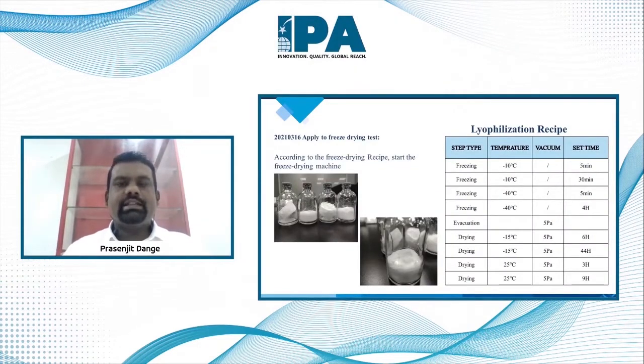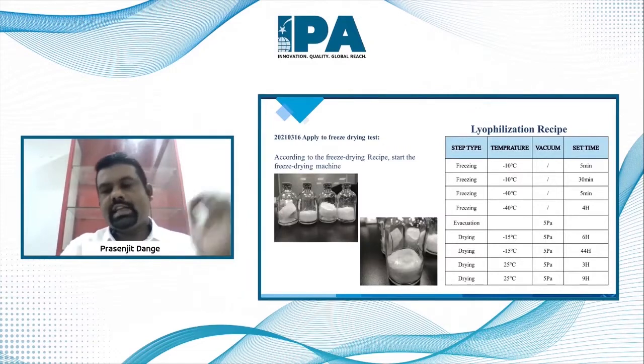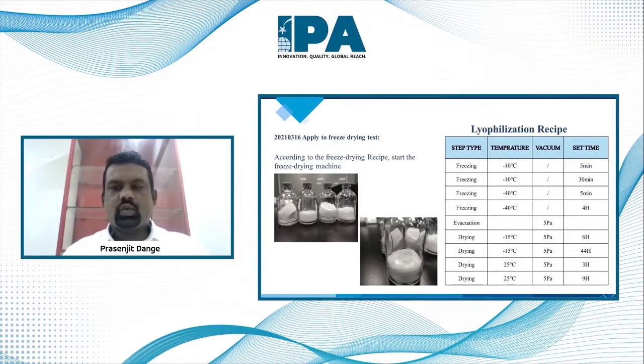Yeah, so we applied this particular recipe in the freeze dryer, where you can see the recipe on the right side, with freezing done at minus 10 for 5 minutes, then another freezing at minus 10 again for 30 minutes hold, and then freezing again at minus 40 for 5 minutes as a ramp and 4 hours as a hold, then going for the vacuum and the drying. This recipe was applied to the same product given by the client, and according to the freeze drying recipe, we started the cycle and got the results as shown on the left side in the picture. Now, with these pictures, can you go to the next slide for the conclusions?